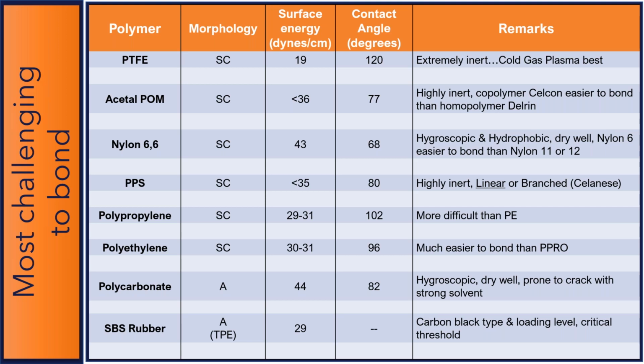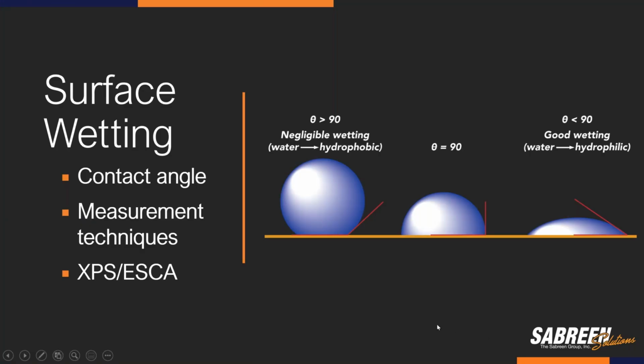Lastly, I'm going to talk about SBS rubber and other types of thermoplastic elastomers, which also are amorphous, but this is one of the biggest breakthrough areas that we're advancing right now. And what we have found is that the type of carbon black that's used in the rubber and the loading level has great significance to the ability for adhesive bonding. We've determined there's a critical threshold level of the letdown and the type. Once one has exceeded that critical threshold, it becomes magnitudes more difficult to bond. So always keep in mind that you want to know as much as possible about your polymers and identify what alternatives there may be. We're going to move on to surface wetting, contact angles, measurement techniques, and different types of analytical testing.